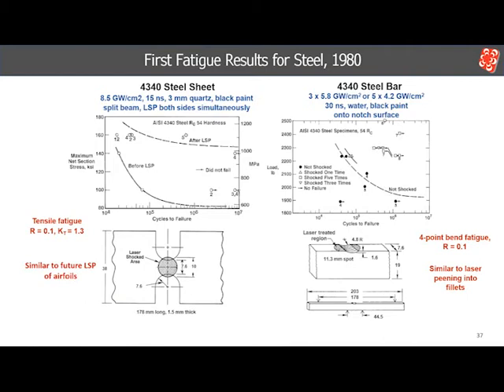Resembling laser peening a fillet, where the main effect is to retard crack initiation. As a crack moves into a laser peen surface on a thick section, the retardation effect decreases with depth as the compressive stress decreases. The steel was tested at a hardness of 54 Rockwell C.